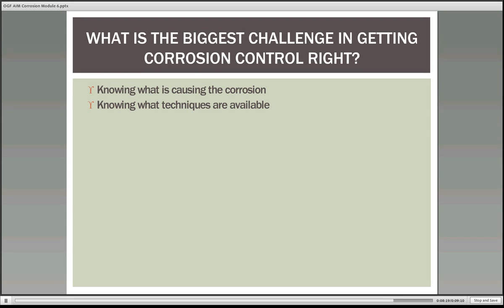The other side of it is the cost associated with corrosion control. If you're not careful, you can spend vast amounts of money on it but not necessarily get control that is sensible. So getting a smart level of corrosion control is a fine balance. Using the right coating matters — there must be 30 to 40 different coating systems available. Which one is best for your system? Do the testing. Very few people do the testing. Do comparative tests, find out which one is best for your environment, and don't just use a standard industry standard test — design a test that closely matches your conditions.